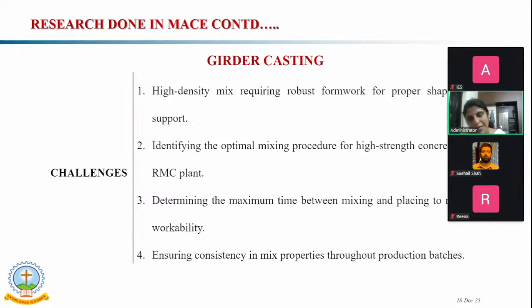That's the laboratory practice. But when we came to the RMC plant, that did not work. So we did many trials in the RMC plant and identified an optimum mixing procedure there to develop the girders. The next challenge was to determine the time between mixing and placing. After mixing in the RMC high shear mixer, we have to put the mix into the girder formwork. That lapse time is the retention time.